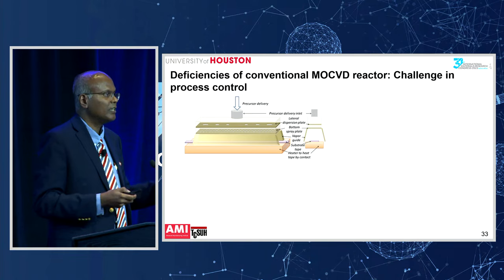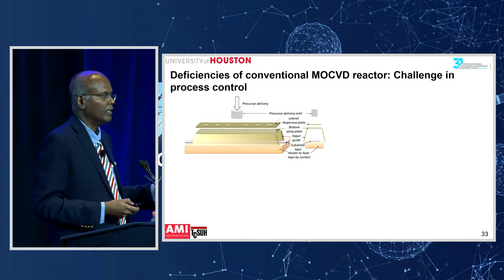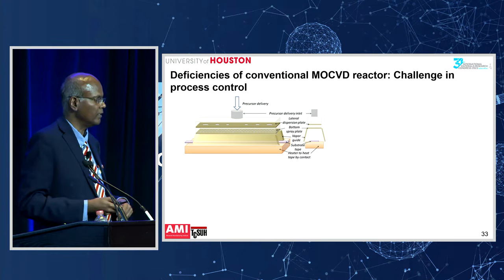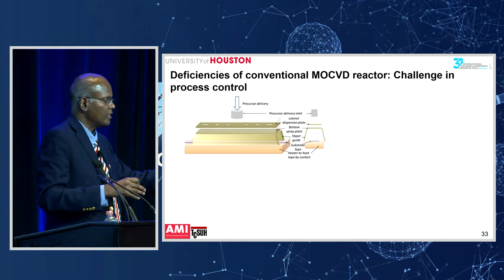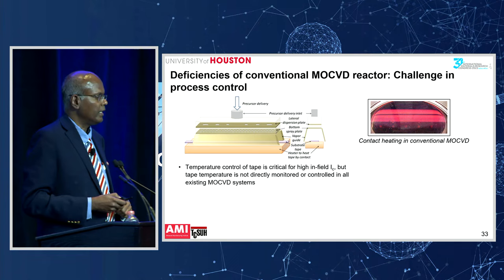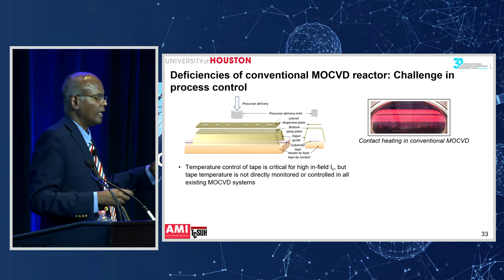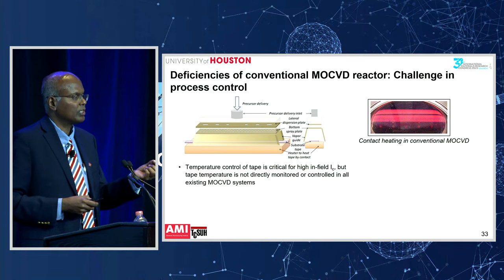So MOCVD, that's the process being used to make these films, make the tapes. I'm showing a schematic of that reactor there. Basically, in the MOCVD process, you're injecting the precursors through a showerhead, and they're depositing the film on a moving tape, which is heated by a susceptor. You can see a photograph of the heating of the tape as it's continuously moving from one end to the other. The thing is, you need really good temperature control when you're growing thick films, but you don't have good control with this kind of heating process.